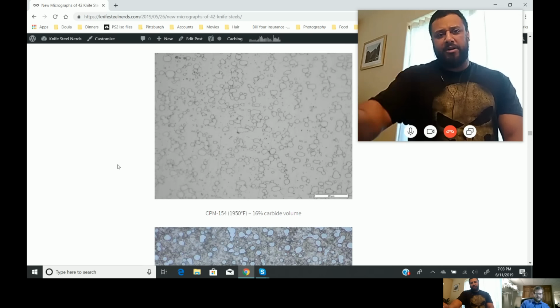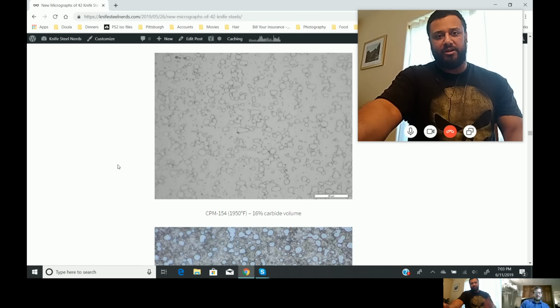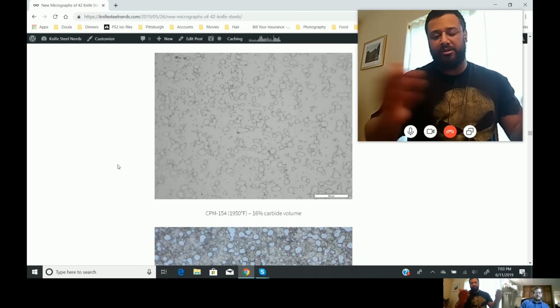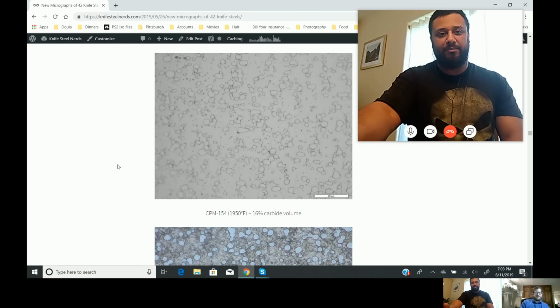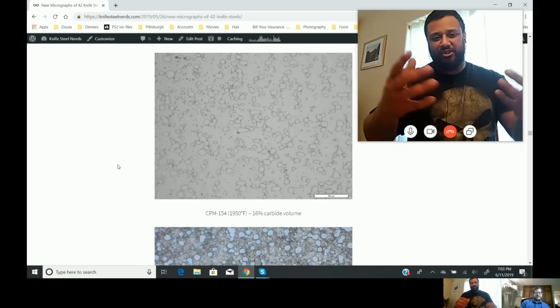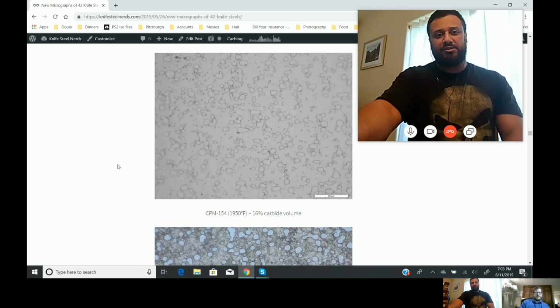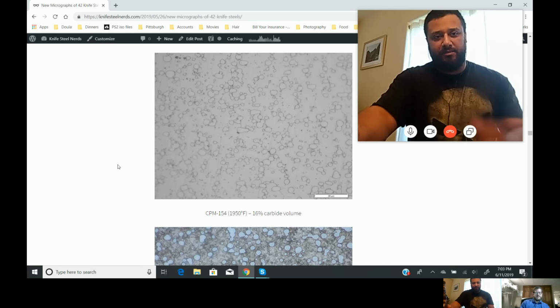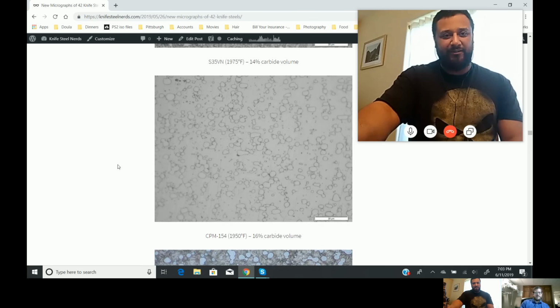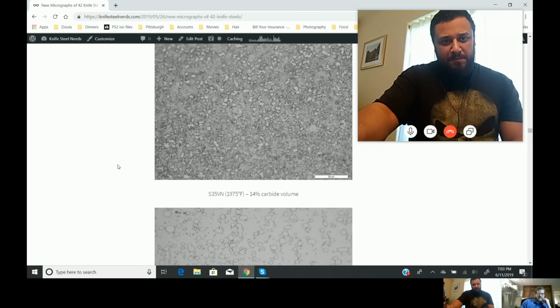I'm really curious about that as well. I have my little goofball nail test that I did where the CPM 154 exploded, but then the S35VN didn't, even though it was 1 point softer, which is probably the most significant factor for why that happened, because it still broke out a chunk on the edge. But yeah, that'd be interesting to see with some more testing because look how much bigger those carbides are, huh? Yeah, so it's really surprising.